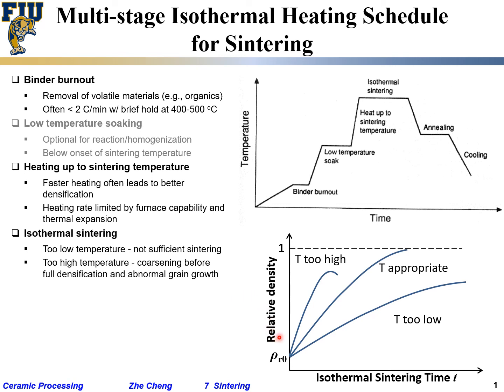Vertical axis is relative density, like from 0 to 1. Of course, quite often we do not start from 0, because when you compact the green body, you start from somewhere around 55 to 65% relative density. Make sense? You do not start from 0 because you packed the green body, powder, together already. And then from there, isothermal sintering time. If the temperature is too low, you end up, after a very, very long holding, still not reaching full density.